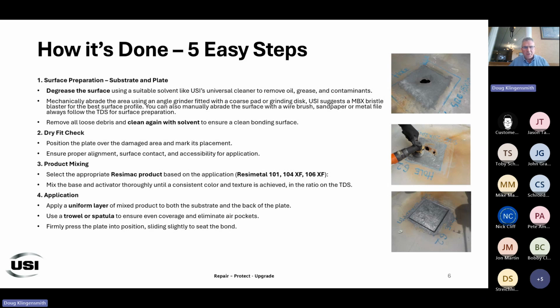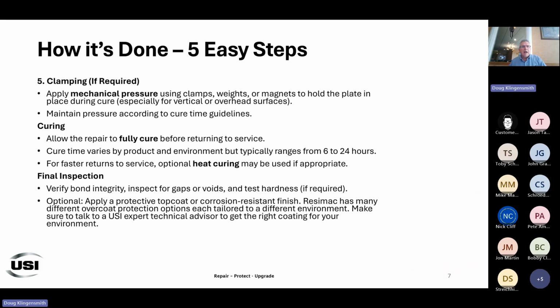We do have our 106 and 104, which set up a little bit faster. So those you can apply at 68 degrees, and they're going to give you about a 4-minute pot life, and then you'll want to apply firm pressure. I've seen people use 2x4s to apply firm pressure, and I've also seen people use clamps, and basically allow the